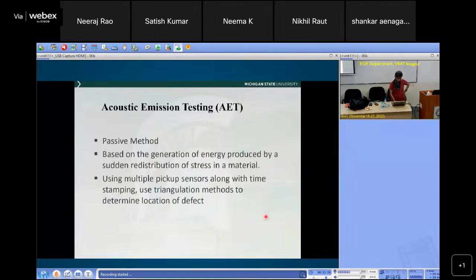So that's ultrasound. There's another method called acoustic emission, and the nice thing about this is that it's passive. Whenever a material is stressed or loaded, it is subject to changes in stress levels, and this triggers the release of energy from the grain structures or atomic level structures in the sample. These will travel to the surface like a shear wave, and then you can pick it up with any ultrasonic transducer. But again, it's very blind.